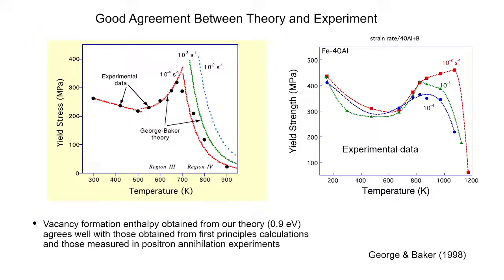And I won't go into this part, but here, this dotted curve is the model predictions, assuming what the vacancy concentration is that you can measure independently using positron annihilation experiments, for example. So the vacancy concentrations can be measured independently, and you can fit it to this. And so this increase is due to the increase in vacancy concentration. But the same vacancy concentration causes weakening at high temperature, because creep is mediated by vacancies, right? So these are the creep equations.